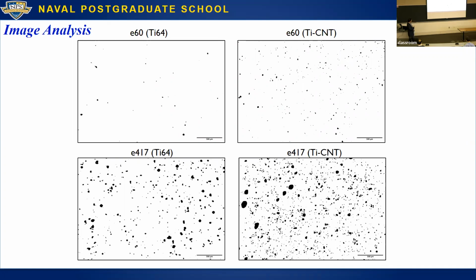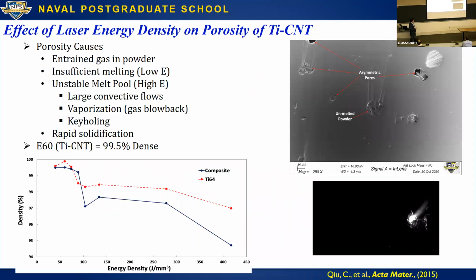So yes, as a function of energy, we get more porosity, and we also get slightly more porosity when we add the CNTs. And we think that's mostly due to, in the lower energy case, most of the milling. The milling is a dynamic process, and you're essentially impacting particles against one another, and you may get entrapped air during those impacts. And at the higher energy, the CNTs are a very conductive phase. They have very high thermal conductivity. For this and for a couple of other reasons, we think that they are increasing the actual temperatures that you're seeing. So here you have an SEM of some of the types of porosity that we encountered in the sample.